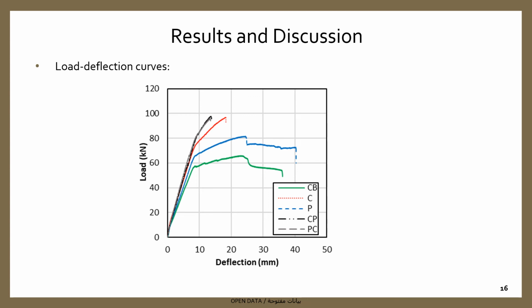However, the strength enhancement was at the expense of ductility, where the deflection at ultimate and failure of specimens C, CB, and PC was reduced compared to the control beam. An unusual behavior was observed in specimen P, where the deflection at yield, ultimate, and failure loads was enhanced. Consequently, the ductility at ultimate and failure of specimen P outweighed CP. This interesting performance is untypical for FRP strengthened beams, and it is a result of the large rupture strain capacity of the PET fibers.